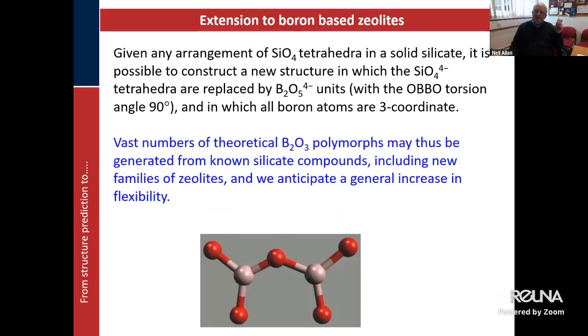But now, however, we've extended that. And one of the things we've recognized is that if you take any silicate based on SiO2, which is based on SiO4 tetrahedra, now that's SiO4 4-, we can replace that with B2O5 4-. Okay, that's not a tetrahedron, but at the two ends, the oxygens are arranged with the same orientation as they would be in the tetrahedron. Okay, there's an extra oxygen in the middle. But in principle, we can do this substitution. So we can take anything with idealized formula SiO2 and turn it into the corresponding boron compound.